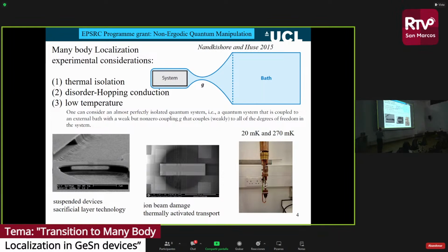So, experimental considerations: thermal isolation. That involves a lot of time in the clean room, but it's great because we're starting with a 2D material, and we're trying to take away some of the layers in the structure to form things like nano bridges, or bridges, not really a nano bridge. The scale bar here is 2 microns. This is an image of a Hall bar, so it's a 2D system. We've etched away underneath the Hall bar. You can see where we've etched underneath here, and we get these completely freestanding structures.